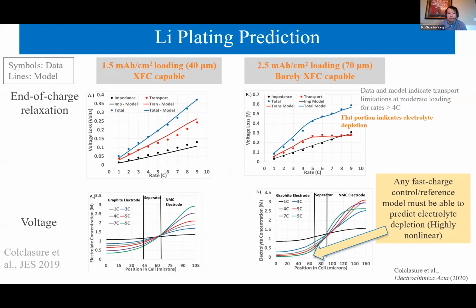Yeah, here we actually try to develop this kind of technology, especially model based. This is some voltage loss, as you can see after fast charging during voltage relaxation. We calculated the impedance and the transport resistance. This is the transport resistance. As you can see at 4C, beyond 4C, there is a plateau indicating this cell stopped charging due to the transport limitation.